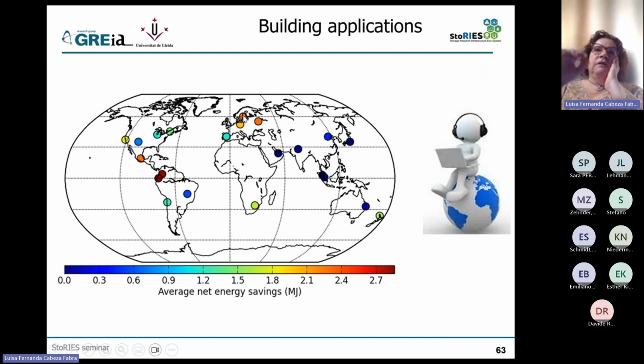And in each one, we selected what our simulations taught us was the best temperature, put the properties of a commercial material on that, and then calculate this average energy savings. And we saw that, in fact, of course, if you have the PCM with the perfect melting temperature for your climate in that location, your average energy savings changes, and therefore your profitability increases.